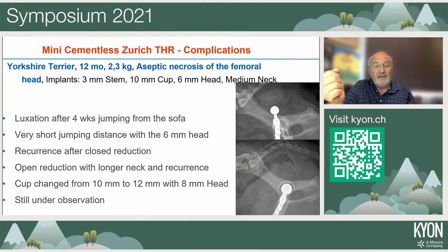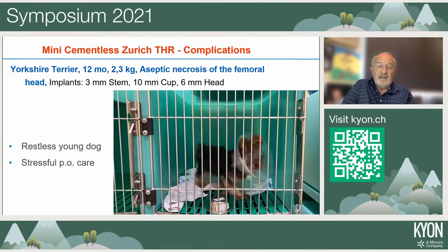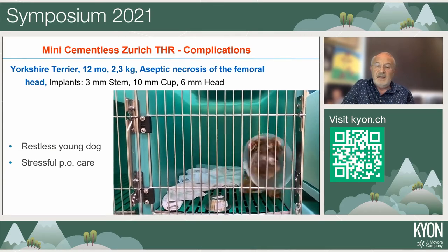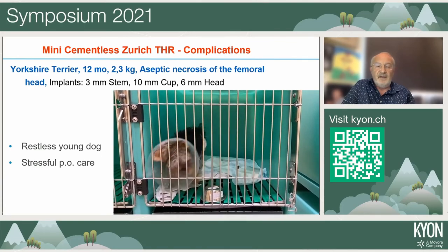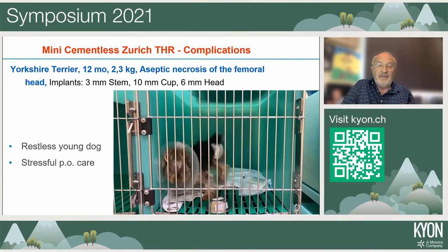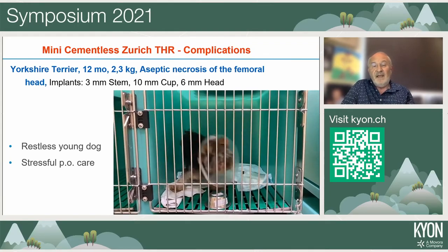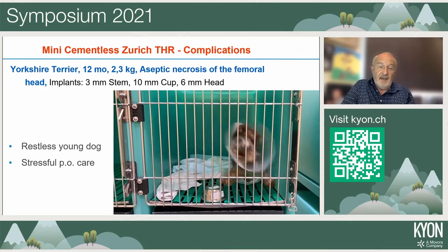We moved the cup from 10 millimeter to 12 millimeter, because the 12 millimeter can allow an 8 millimeter head, which has a better jumping distance. Also, we tried to improve the orientation of the cup to reduce the retroversion and also the angle of lateral opening. And nowadays, as you can see in the image below, it is okay. We are still keeping it under observation, but this is a very demanding puppy. You see, it is never standing, always jumping, always moving like crazy, so very stressful postoperative care. At the moment, 15 days after the revision, it is still okay, and I hope it will remain so.